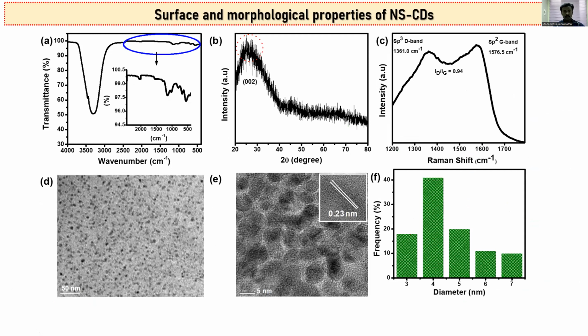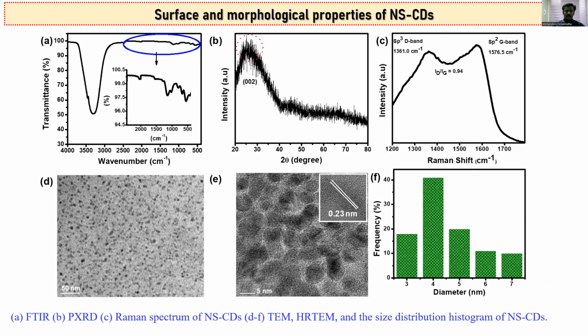The next one is surface and morphological characterization. The surface and morphology were confirmed from FTIR and TEM analysis. The FTIR spectra revealed bands around 3300 and 3200 centimeter inverse, assigned to the hydroxyl or amine stretching vibration. Then major peaks appeared around 1450, and also at 1210, assigned to stretching vibrations of CN, SH, and CS bonds, indicating the presence of nitrogen and sulfur on the doped surface of carbon dots.